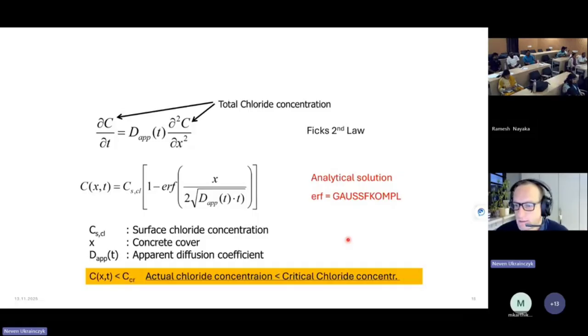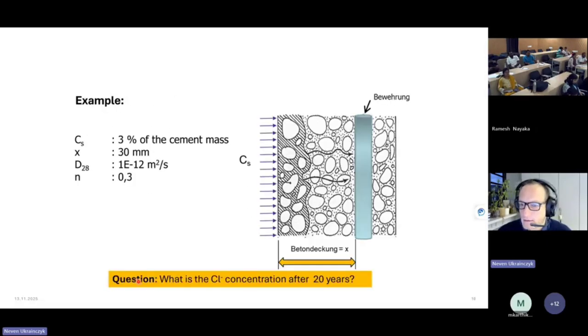So now this is Fick's second law. You can implement this in Python, Excel, wherever you want. And we want to predict when the chloride at the cover depth, at the steel level, reaches the critical chloride content. And when it reaches the critical chloride content, then we need to do maintenance. We should remove the old cover contaminated with chlorides and apply new repair mortar.